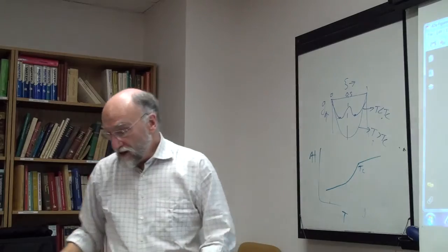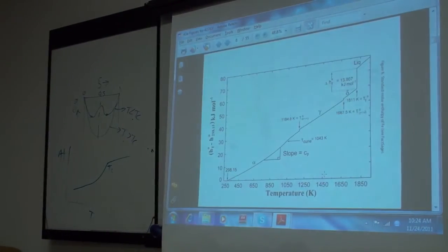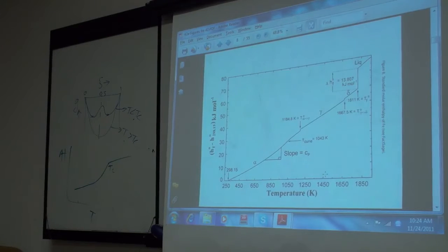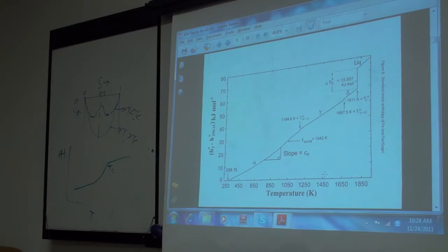And as I said yesterday or 2 days ago, it's the same thing with the silver-copper thing. As you heat the silver-copper up to the critical temperature, over the last 30, 40 degrees, you start to get an increase in the heat capacity, and then a second-order transition occurs. So this is a second-order transition. There's a change in slope, but there's not a discontinuity. Okay, the first-order transition, such as the melting point, is a change in H, whereas here it's just a change in slope.